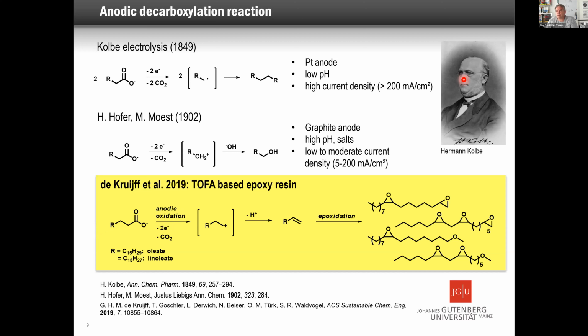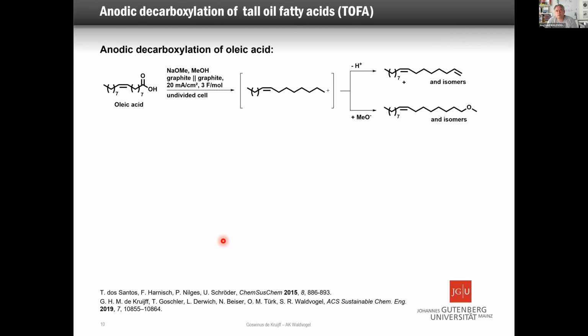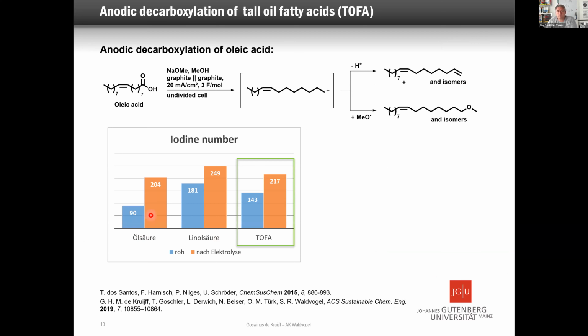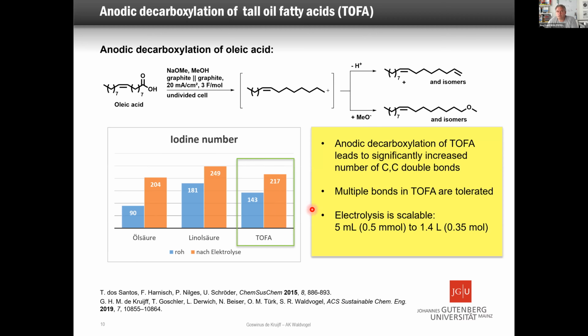And the important thing is definitely, if you have something like this, then you are able to have systems with multiple double bonds. If the double bonds are epoxidized, then you have multiple epoxy groups there, which are of course of interest for making resins. And that's what we indeed did here. We used oleic acid, but also TOFA. This is the oleic acid, linoleic acid, and this is TOFA. By electrolysis, you enhance the iodine number. The iodine number just tells you how much iodine would be consumed if you remove the double bonds. The bigger the orange part is, the better it is because you have more double bond equivalents in there. And if you have it there, the other double bonds don't make problems in this reaction.